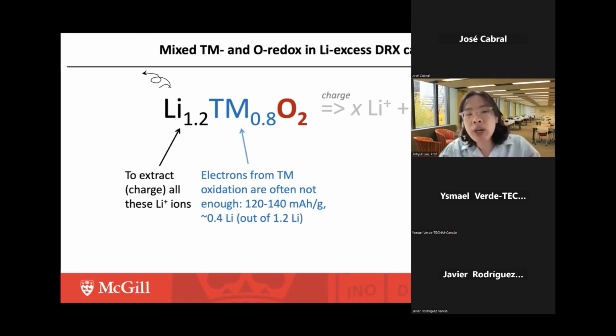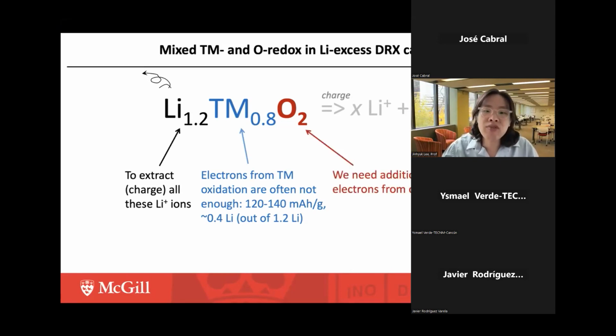So if we want to extract the remaining lithium from the structure, then we need an additional electron source, right? So where do we get this electron? We get this electron from the oxygen getting oxidized. So this is the reason why, to operate this lithium excess DRX cathode, it is important to understand both the transition metal oxidation, or say reduction, combining we call it redox, right? So it is important to understand the mix of transition metal and oxygen redox process to actually achieve high charging and discharging capacity,